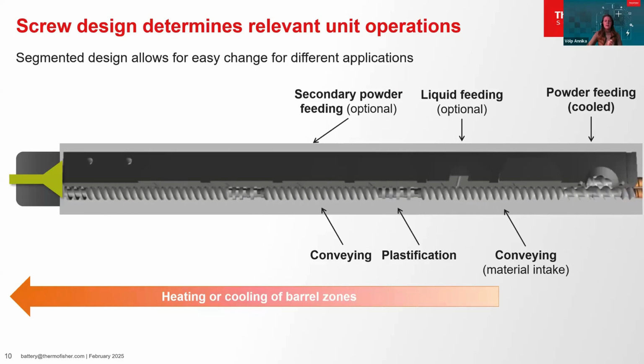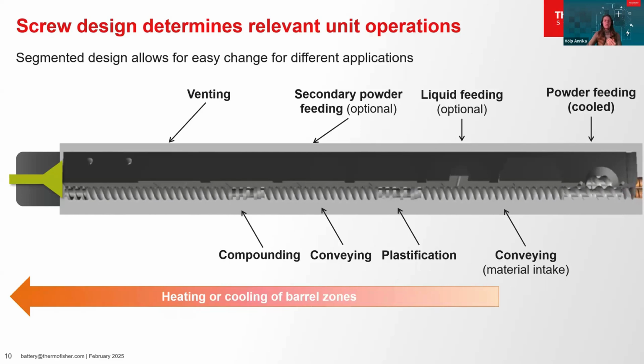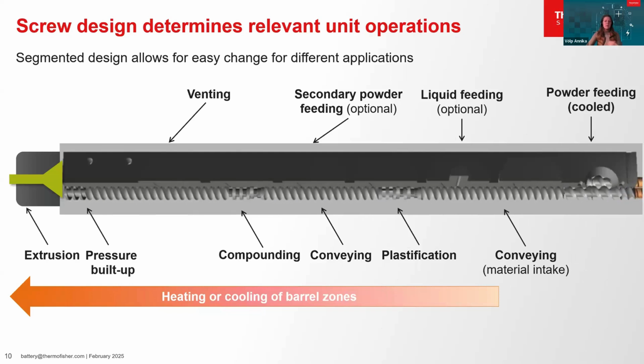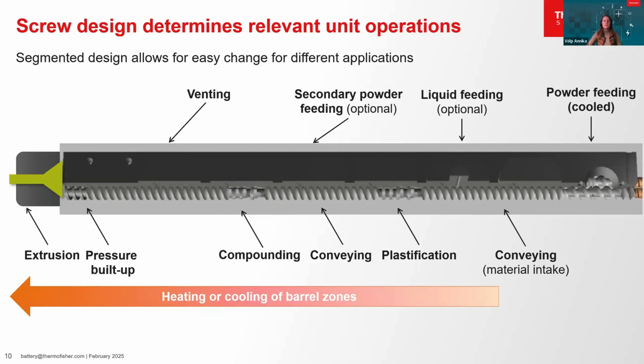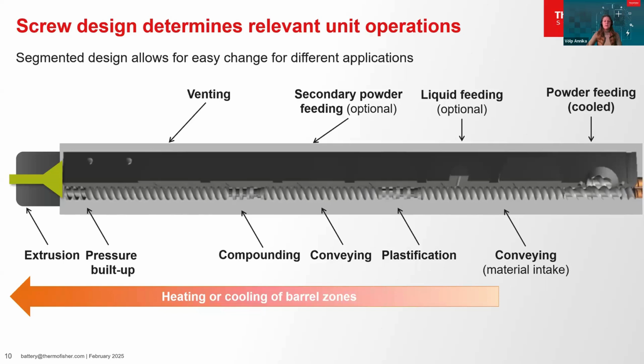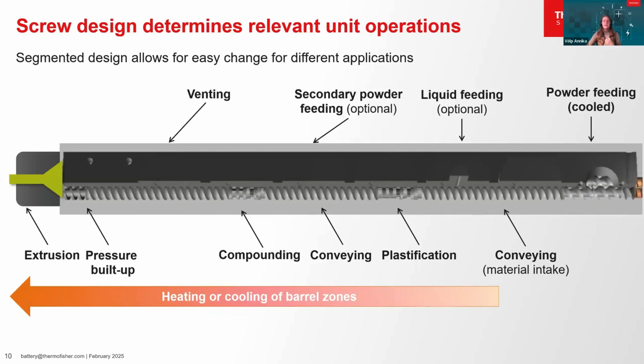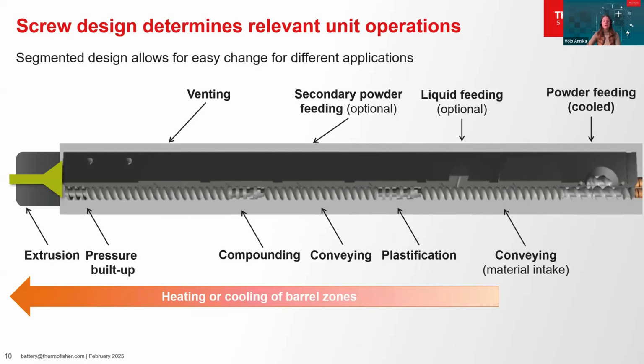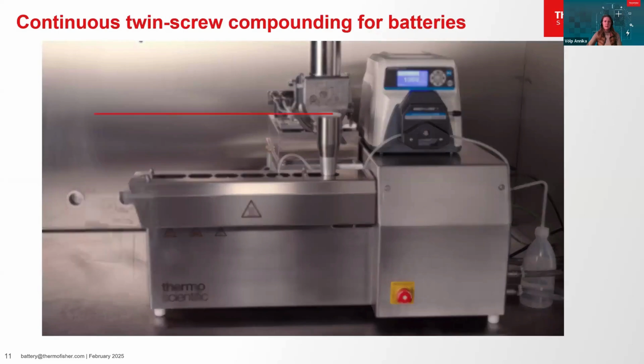The first kneading zone plasticizes the material by shearing. A second conveying zone allows for secondary powder feeding. The next compounding zone mixes all materials. And in the third conveying zone, gases could be removed by venting the barrel. Finally, the pressure is built up and the material is pushed through the die. The screw design is specific to the material and the unit operations that the material is supposed to undergo. Some battery mixing applications can be realized with the appropriate twin screw mixer designs, and they are highlighted on the next slide.